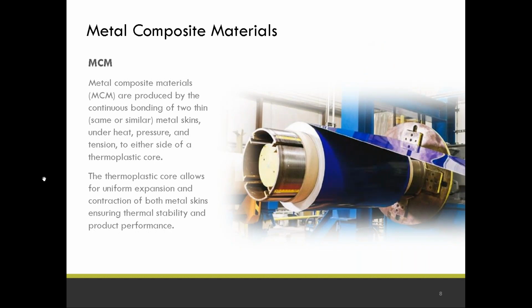Let's talk about metal composite material for a minute. They are basically a composite material that's produced by the continuous bonding of two thin skins, metal skins, under heat, pressure, and tension to either side of a thermoplastic core. The metal skins are typically aluminum, although they can be stainless, copper, zinc, or even titanium. The thermoplastic core allows for uniform expansion and contraction, and it assures thermal stability, no oil canning, that type of thing, and evens out the product performance. So the core is a very important part of a composite.